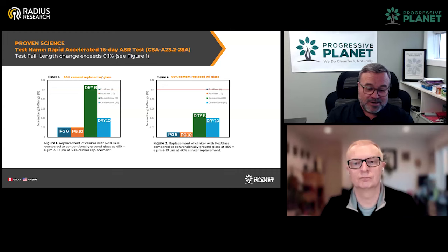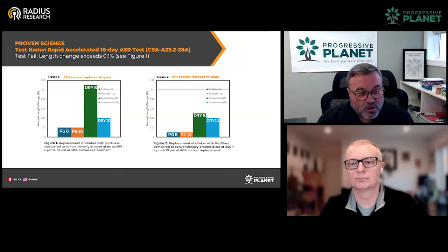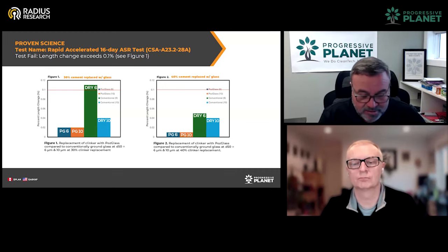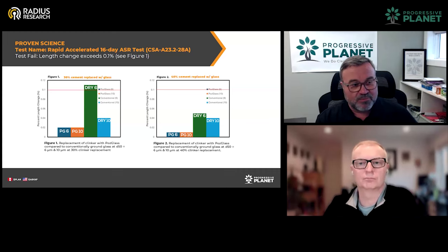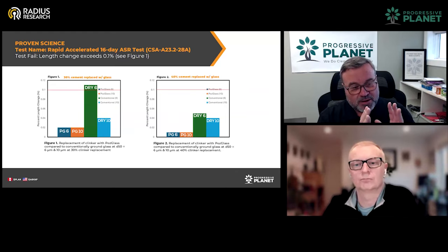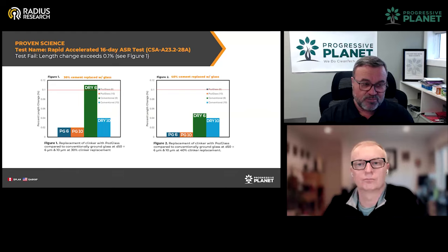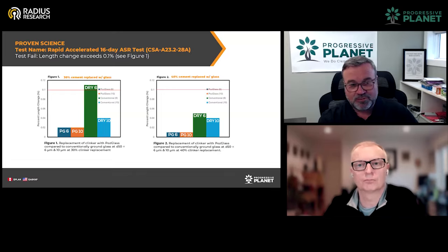So we are delighted to show these results, and I hope with this explanation that it may be a little more clear to people. But all cement particles do not dissolve. They're only surface active. What we do is remove the sodium from the surface of the PozGlass particle so that it's not part of this reaction. And this is very clear evidence of the efficacy of what we're doing with the wet grind.